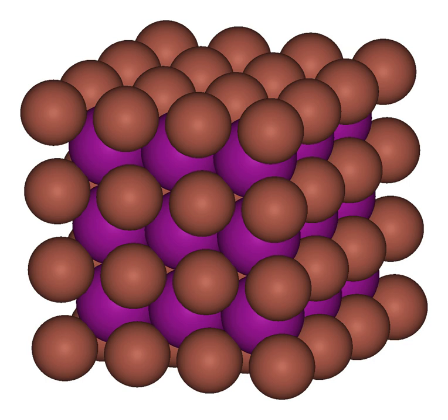Thallium III chloride. TlCl3 has a distorted CrCl3 structure like aluminium chloride and InCl3. Solid TlCl3 is unstable and disproportionates at 40 degrees Celsius, losing chlorine to give TlCl. It can be prepared in CH3CN by treating a solution of TlCl with Cl2 gas.